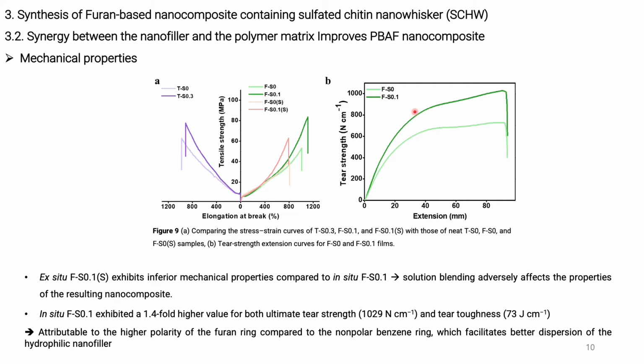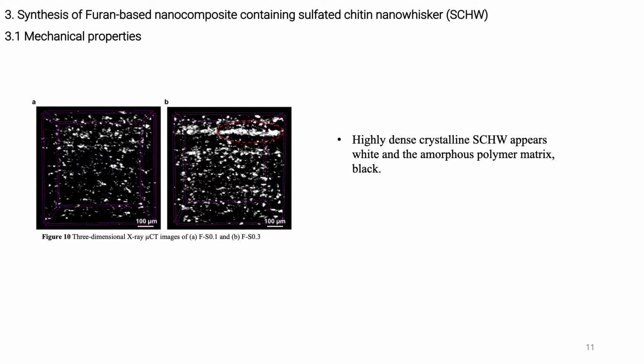The superior effectiveness observed for FS0.1 is attributable to the higher polarity of the furan ring compared to the non-polar benzene ring, which facilitates better dispersion of the hydrophilic nanofiller. Also, the good filler dispersibility in butanediol effectively prevents the resultant nanomaterial from aggregating. This is further supported using 3D X-ray micro-CT, as we can see here in figure number 10, where highly dense crystallized SCHW appears white and the amorphous polymer matrix appears black. As can be observed, the fillers are evenly distributed throughout the PBAF matrix at 0.1 weight% loading.